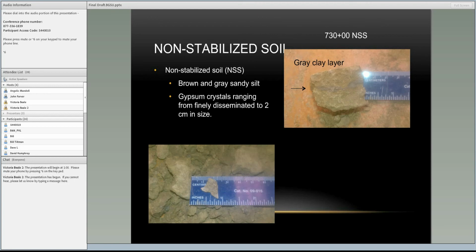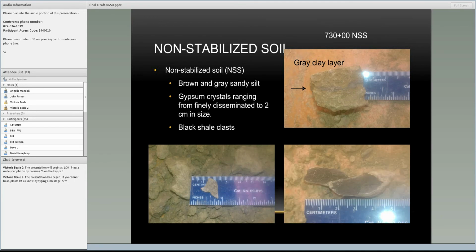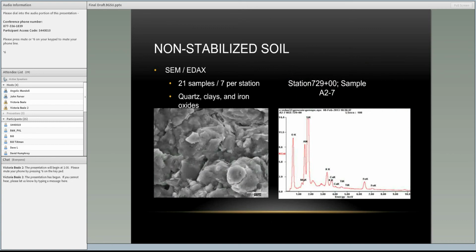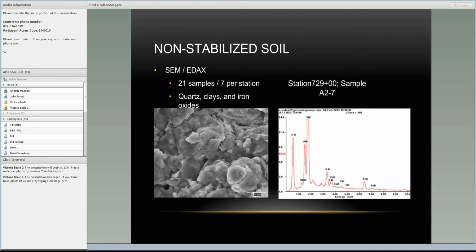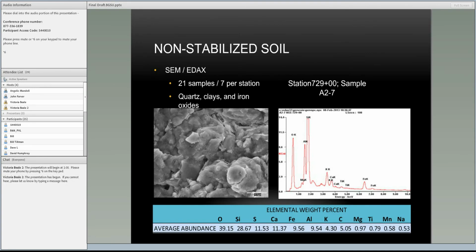So what we did first was look at the non-stabilized soil with SEM and EDAX. And these results are based on 21 samples, 7 samples per station. And this right here is a typical SEM image with a typical EDAX spectrum. So what we're looking at is a sample of station 729 here. And non-stabilized soil, as you can see, it's just this very platey, flat image that you get of the soil. And then here is average elemental abundance for the 21 samples. So you're getting a lot of high oxygen, silica content, a lot of calcium and iron and aluminum with some minor amounts of potassium and magnesium, titanium, and sodium.